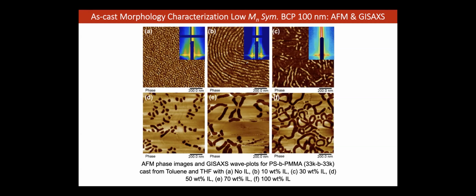By the way, the interesting thing, Bennett didn't actually answer the question why adding ionic liquid makes the structures go perpendicular. In fact, that was not discussed at all. So we think the reason is, it's very interesting, ionic liquid doesn't like the silicon substrate. PMMA has a strong attraction by itself in its pure state to the silicon substrate and polystyrene dewets. But ionic liquid likes PMMA, so it doesn't like the substrate, and PMMA likes the substrate. So when it goes into PMMA, which it likes, it actually cuts down the interaction with the substrate enough to make it neutral with polystyrene. That is our working hypothesis, but we need to do a lot more.